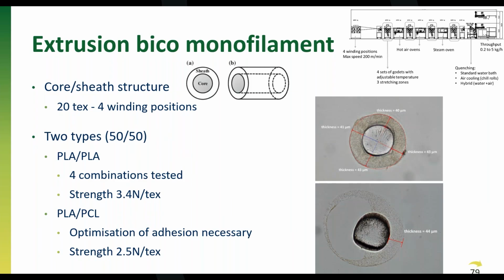We have 4 different winding positions, so we produce 4 filaments at the same time of around 20 tex. And we tested 2 types. As said in the beginning, we have 2 different demonstrators, PLA and PLA-PCL are required for those. 4 different combinations have been tested for the PLA, so 2 high melting and 2 low melting grades. And here we can achieve a strength of 3.4 Newton per tex, which is a little bit lower than the 4 Newton per tex that was required. On the right-hand side, you can see a picture of the cross-section under the microscope of that fiber, so with a nice core sheath structure.